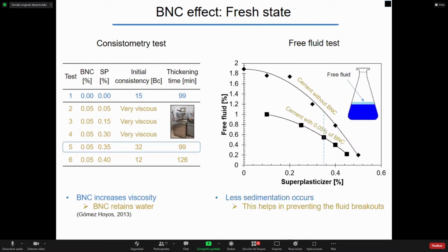When we let this mixture sit under static conditions for 2 hours, we can remove the free fluid from the top, which is separated from the mixture, and compare it with the total weight of the mixture. In this case, the free fluid depends on the superplasticizer content, and we see that it decreases with the content of superplasticizer.